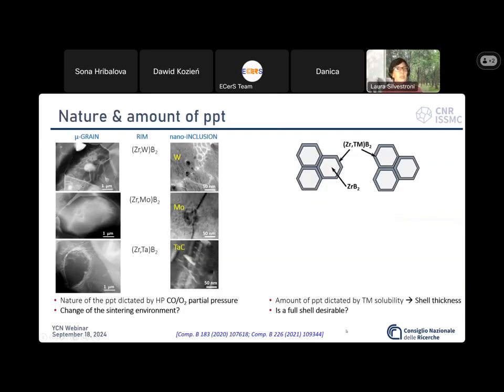Another interesting aspect which we found working on several systems containing zirconium diboride and tungsten, molybdenum, or tantalum, is that depending on the system, on the transition metal, we observe precipitation of inclusions of different chemistry, borides, metal, carbide, and shape. And we suppose this factor to be related to the local partial pressure within the furnace. One question that we still have in mind and haven't answered yet is the possibility to tune the chemistry of the precipitates in the form of metal borides or carbides by using different furnaces, by changing the sintering environment. We still don't know if it's possible or not.